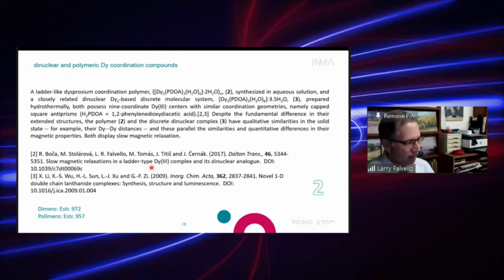Now, if the crystal is triclinic, and as I say, you have one molecule in the unit cell, then you do gain with respect to the information you would have if you measure from a powder. But if we look at our other two groups of complexes, this may be instructive, because you don't always get the full molecular tensor depending on the symmetry of the crystal. For a second group of compounds, a pair of dysprosium PDOA complexes. We'll see what PDOA is in a minute. One is a polymer with a staircase-like structure. One is a dinuclear complex with a fairly large distance between the two dysprosium atoms.